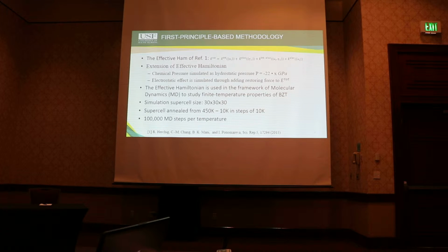To study the finite temperature simulations, we use the effective Hamiltonian approach, where the basic Hamiltonian is shown here. For the effect of the negative chemical pressure, we use the hydrostatic pressure P, which is shown here. And then for the electrostatic effect, we added a restoring force into the effective Hamiltonian, and then used that effective Hamiltonian as the framework for the molecular dynamics code to study the finite temperature properties for BZT.